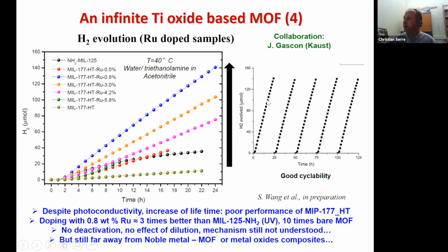Anyway, what is interesting in terms of performance is that there's no deactivation observed. If you take NH2-MIL-125, you see that there's a deactivation, probably because you use an amine that gives a slightly basic pH, and then this MOF is less stable than our MOF. And we could recycle it 5 times, so no deactivation, it is really stable with time.